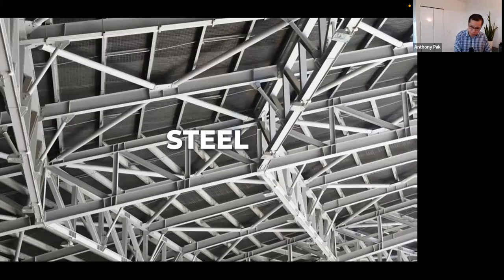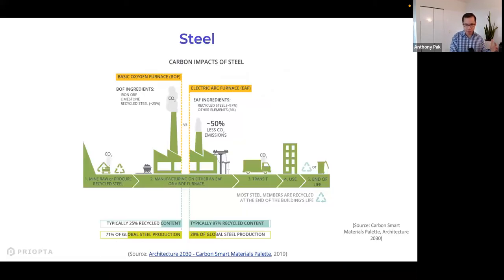Next thing is steel. So just to give you a high level overview, there's two main ways of producing steel: basic oxygen furnace and electric arc furnace. So basic oxygen furnace is how we produce most of the primary steel. It accounts for about 71% of global steel production. It has much less recycled steel content. This is how we produce the primary steel. And it's much more emission intensive, sometimes 2 or 3 times higher emission intensity than electric arc furnace.